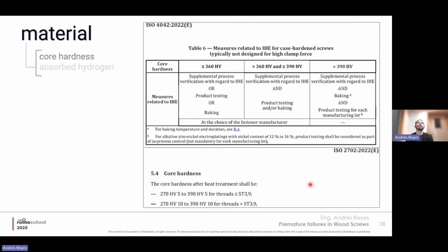Optimal storage environment concerning hydrogen embrittlement: it's any environment that wouldn't expose them to corrosion and/or to a source of hydrogen. So the dry condition would limit the entrance of atomic hydrogen, but would also block or stop any possible source of corrosion. So this is what we try to avoid, and this is why it's important to store them in dry conditions. So keep them dry and keep them unexposed to sources of corrosion, which could also be salts.